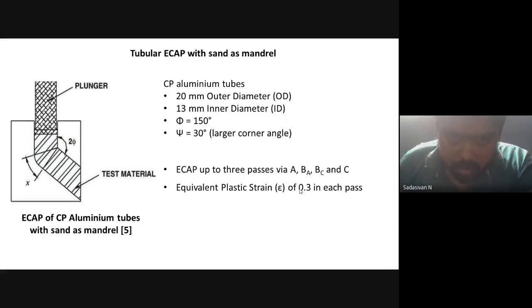Plastic strain is imparted, so there is no change in cross section of the material. Normally we cannot measure the strain here, but we can find it out by numerical methods, finite element simulations. Then we can validate the simulation by taking micro hardness values across the cross section, and the trend of variation can be compared with the finite element strain contour. That's how people validate their FEA simulations with the real test, because the strain is not measurable here; the same cross-section is maintained after the process. It comes to around 0.3 plastic strain in each pass of this process.